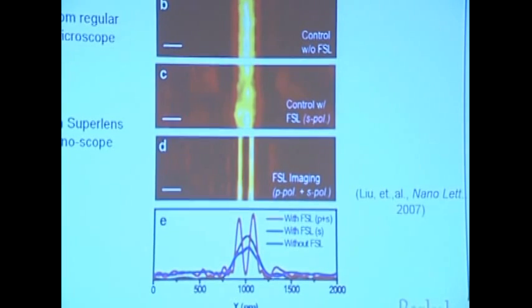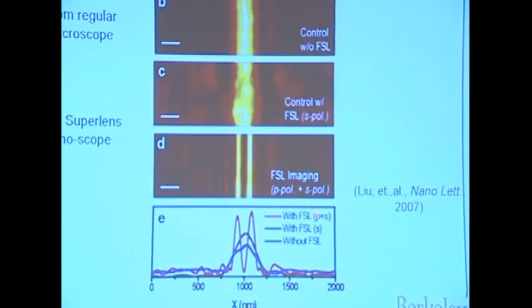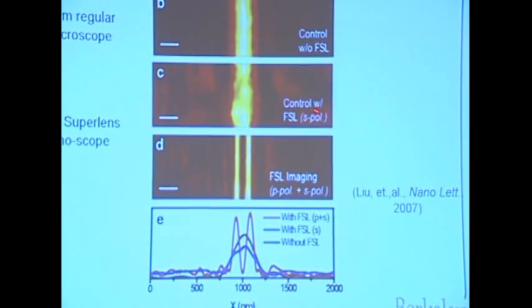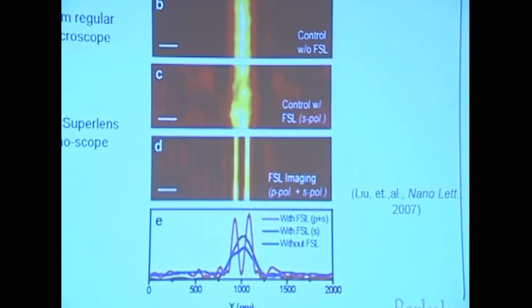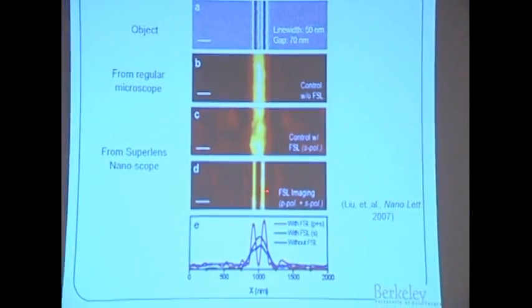It's interesting because this is a plasmonic system. If you use only S polarization, you essentially turn off the surface plasmon, and you're not going to see this enhancement across this slab, such that it gives you a blurred image. But if you use P polarization plus S polarization, that excited surface resonance gives you a very clear image. So this is a cross-section of this image.